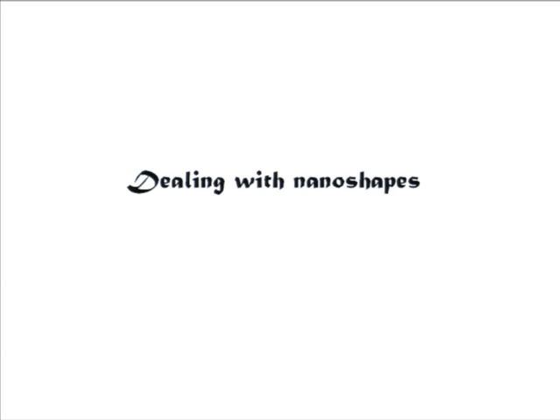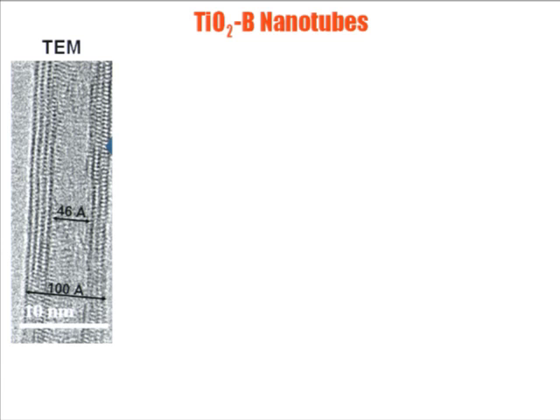So I will show you a more recent example, and this is an example of TiO2B nanotubes. This appears to be a very important material as anode material for future lithium batteries. And you can readily synthesize these nanotubes. Here the TEM is shown, and you can see that the outer diameter of the tube is 100 angstrom, inner is 46.